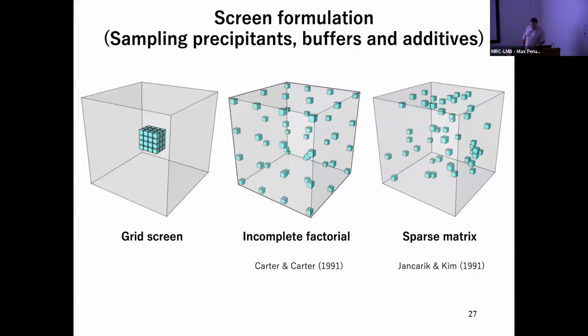A grid screen, left, consists of a systematic approach to screen formulation. So you have 3 parameters, and you basically very rationally vary them. Obviously, you can't reach that much chemical space. You can't do a very narrow range of concentration. You can't test that many reagents. So there's a limit to grid screens. Because of the large number of reagents well suited for crystallization, an extensive grid screen would include millions of combinations, in fact. So it's technically not feasible.